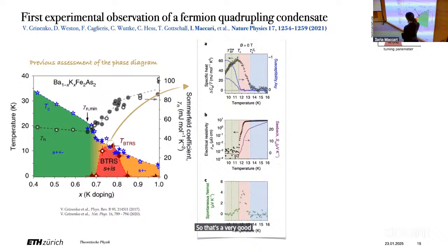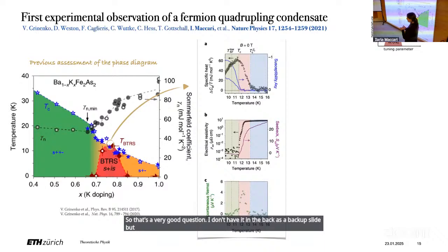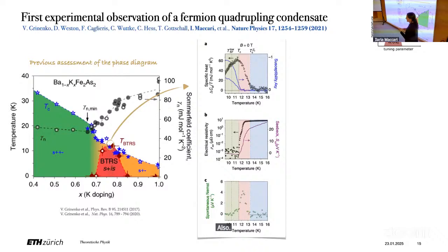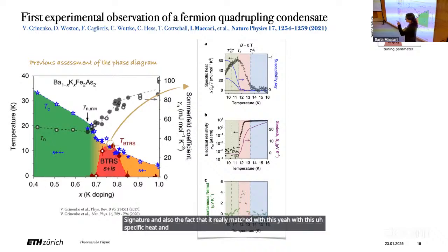I don't have it in the back as a backup slide, but they did check via STM whether there is some instability, of course, in some other channel, and it seems not to be the case. Also, there are no magnetic impurities that could explain this signature, and also the fact that it really matched with the specific heat and other signatures, like in ultrasound, where you see that some modes that couple with the phase difference change slope exactly at that temperature.